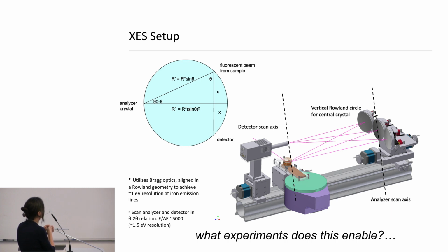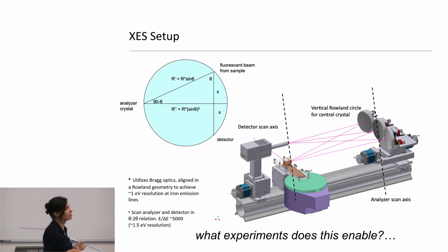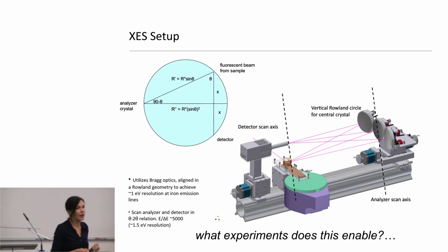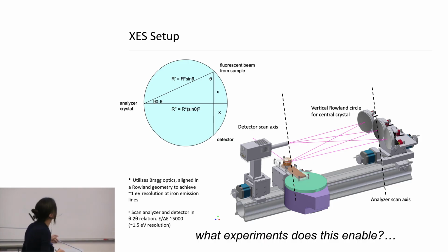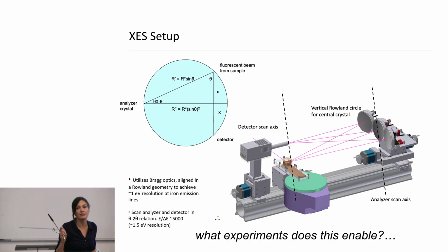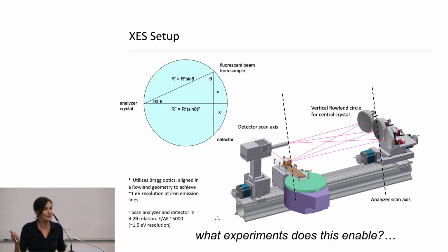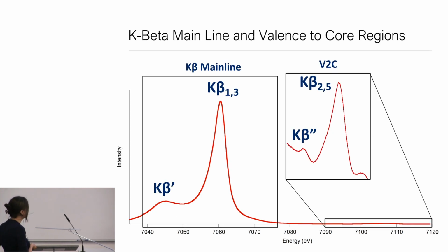And then this will have an angular relationship, which will actually define the energy of detection at the crystal. So again, I'm just using Bragg's law, but because I have ideal crystals, I can go from having a resolution of 175 eV at iron to a resolution of 1 eV. And then these become much richer, much more informative spectra. In fact, I will say in the soft X-ray regime, there are setups that have hit records of 10 millielectron volts. So again, not standard experiments by any means, but this is a field that is evolving.